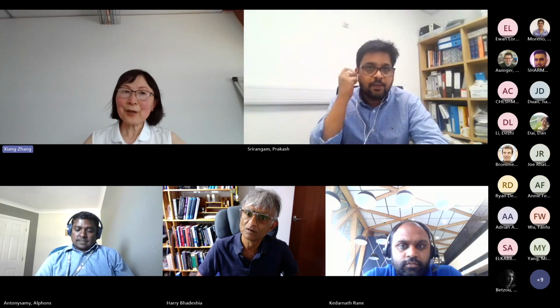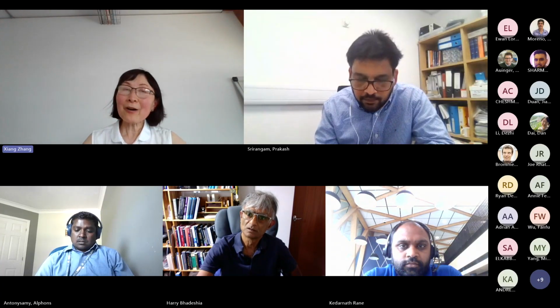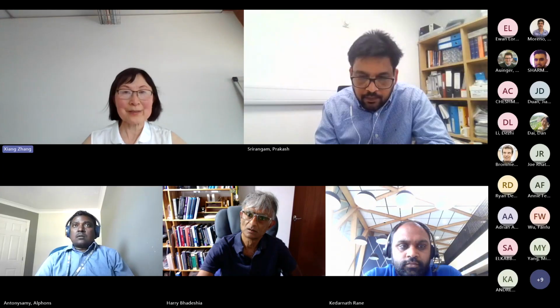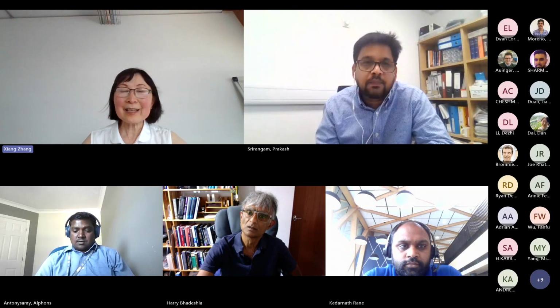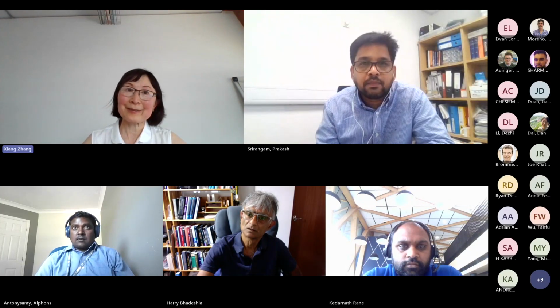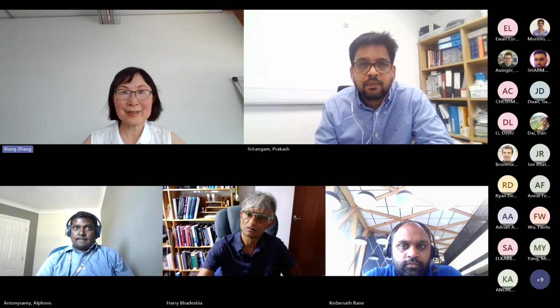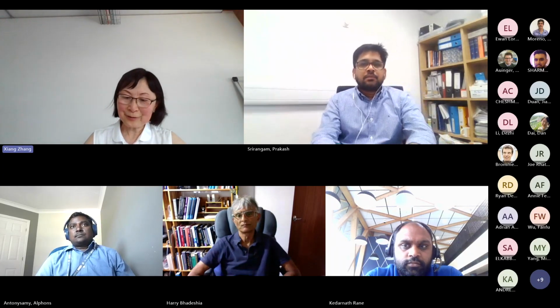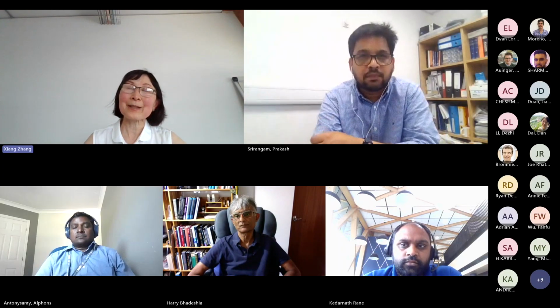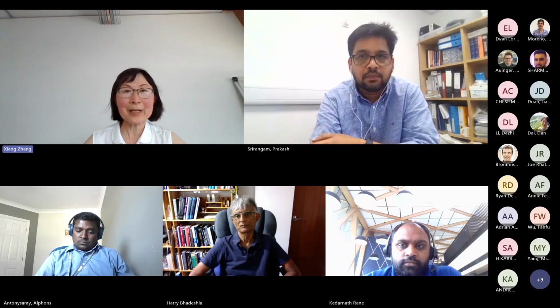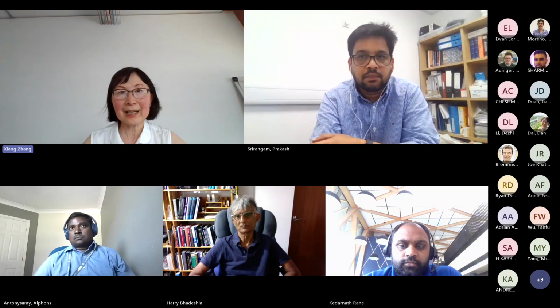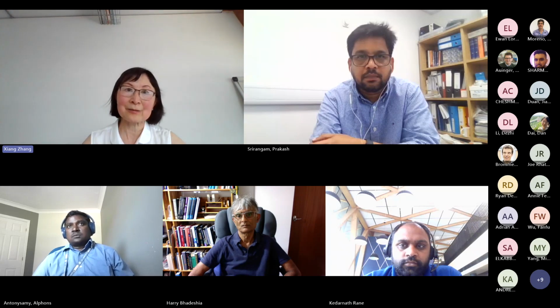Yeah, that's a very good question, Professor Harry. The powder bed fusion people always do that because they have a lot of turbulence in their build chamber. They have entrapped gas pores. And for Cranfield-made wire arc additive manufacture, layer by layer, they probably overlap a lot. And so we don't find it necessary for titanium. However, they do it for steels.